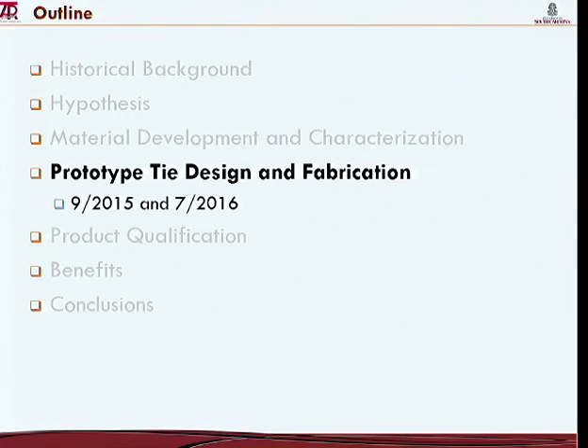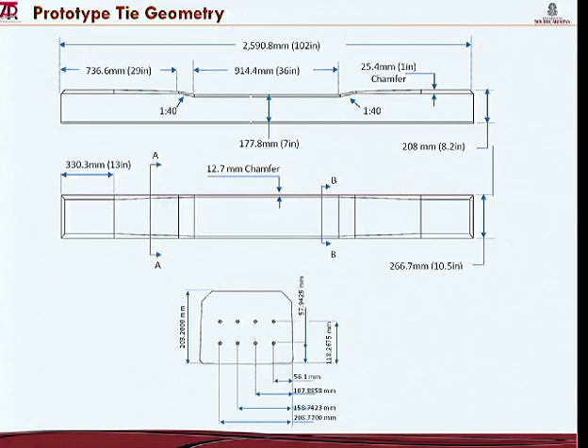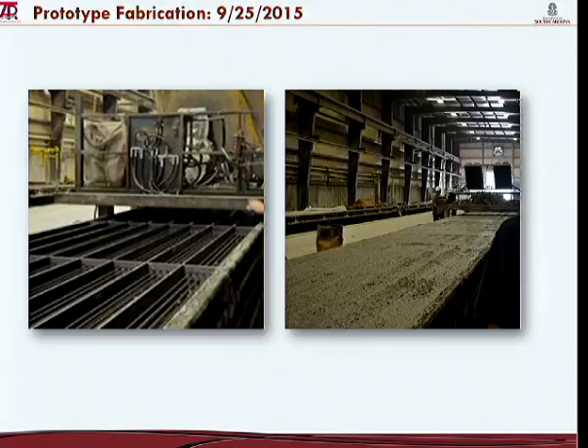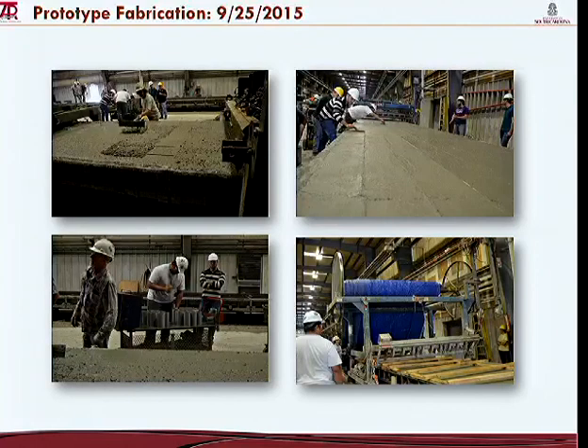So we produced ties in September of 2015 and July last year. This is the geometry. Eight 7-wire strands is the reinforcement here, and this is at the plant the first time we visited. The cavity is filled with concrete, and here we do some surface preparation because we will be using DIC measurements to obtain transfer lengths, taking material for testing samples.